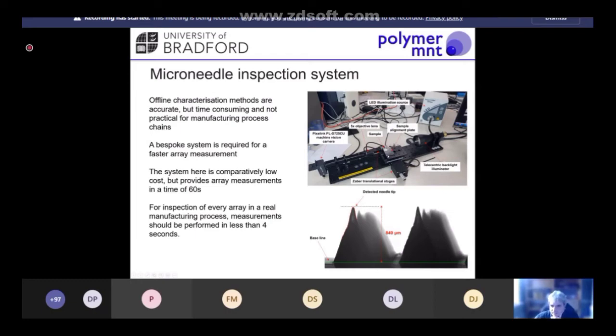So the way this works is we have our array at a slight angle, and it's on an X and a Y stage here that traverses around the microneedle array, bringing a needle into focus at a particular time. And once it's in focus, we fit an edge between the dark and the bright pixels. And then we can use that to measure the height of the microneedle and also the sharpness of the tip. So this is still a fairly low cost system.